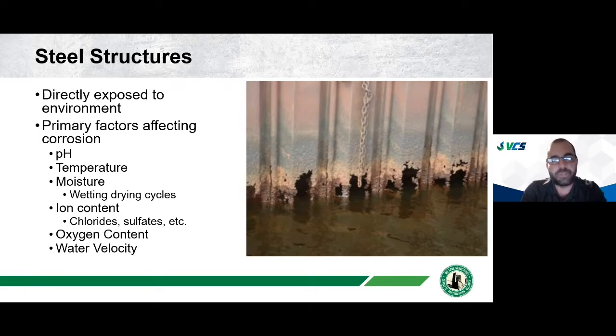Say, typically on a berth, a boat is always being berthed in the same position, and the bow thrusters are in the same spot, you'll tend to see more advanced corrosion in those areas, because the water flow and the jets that are pushing water onto the structure will cause more accelerated corrosion in those areas.